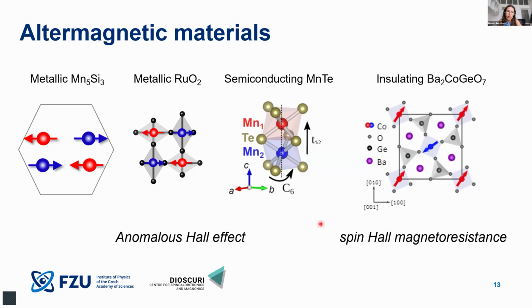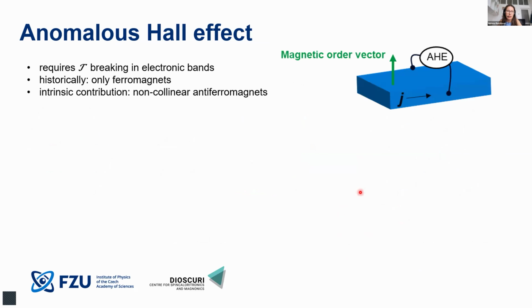And so how do we test the spin transport in these altermagnetic systems? In these conductive materials, what we can easily do is test it via the most simple effect, which I showed before, the anomalous Hall effect. In insulating systems, what we decided to do is to explore the so-called spin Hall magnetoresistance, which, if time allows, I will also try to describe in more detail. Since I said that we are using the anomalous Hall effect as a transport tool to test the presence of altermagnetism,